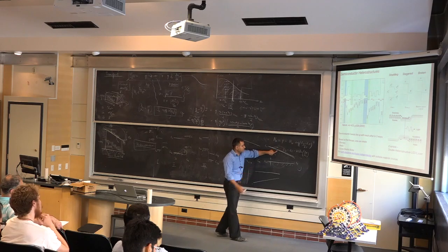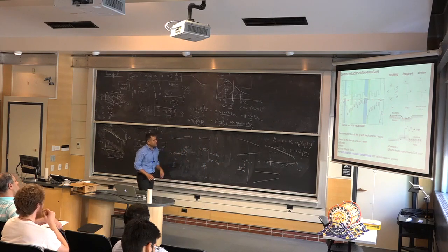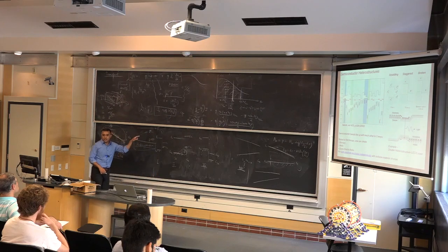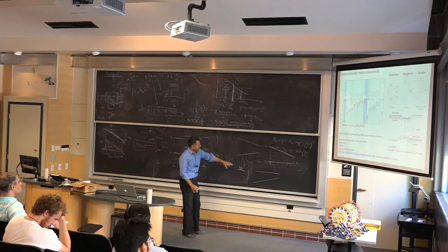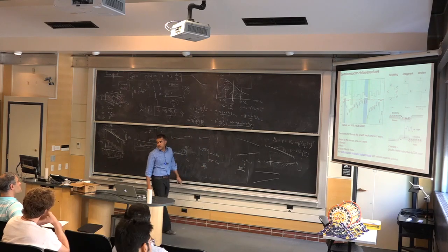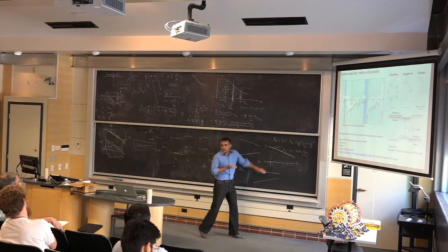So this is called a SiGe HBT, heterostructure bipolar transistor. I think most of them are produced in the Fishkill facility not too far from here, in IBM, silicon germanium HBT technology, and then it reaches about 300 or 400 gigahertz now, very fast devices. And they make use of this quasi-electric field to speed up the device.